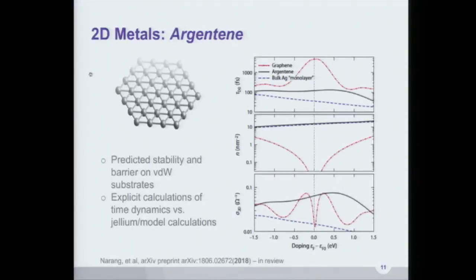I will add that in the time that we wrote this paper, and it's now in review, we found out that there was an experiment that came from a group that made 2D gold, so Aurene, and they were able to stabilize it on a whole host of substrates using a magical chemical technique to make it. When I was thinking about this, I was thinking, oh, somebody's going to do some kind of fancy ALD, or maybe, so this is a theorist's ignorance of how people make materials, but I thought to myself that it'd be a physical technique of some sort that could maybe get to this, and then you would immediately encapsulate it. But they showed that you could actually do this in a kind of solution-based type thing, and that once you formed the layer, it would be stable and it would just kind of float off. So I was pretty excited about that, and I hope people can do something similar with argentene. But that was an excellent question.